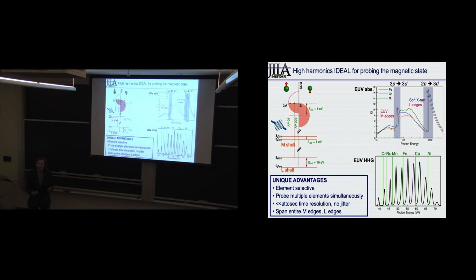So it turns out high harmonics are very interesting to probe magnetic material. This is a little spectrum of the high harmonics, and at the M shell absorption edges, they span nickel, cobalt, iron, manganese, ruthenium, and they're very nice. We can shine this on an alloy or a multilayer, and so we can probe the magnetic state of each element in the alloy or each layer in the multilayer. That's what is nice. You can't do that with other techniques, and we have very high time resolution. So you can think about this as either the shorter wavelength version of visible MOKE or the longer wavelength version of soft X-ray absorption spectroscopies.